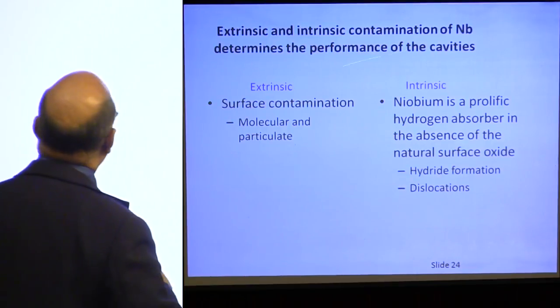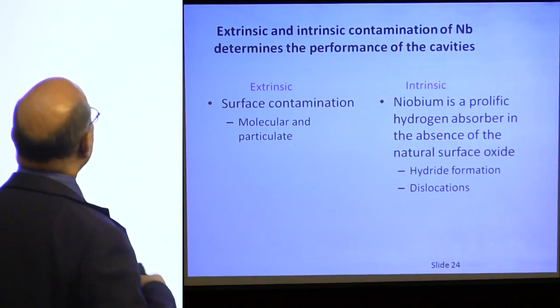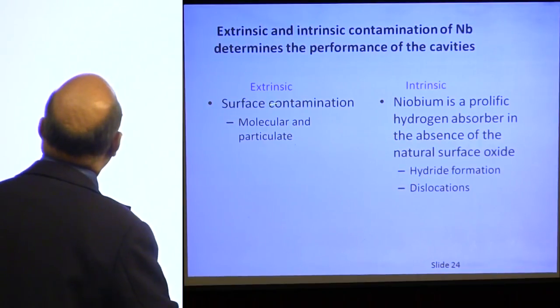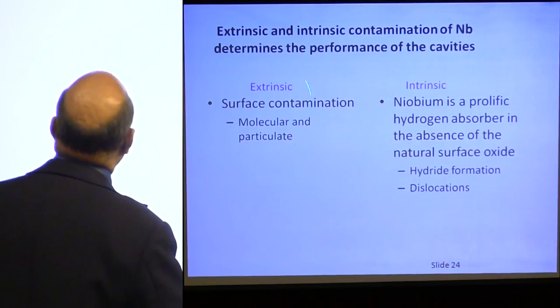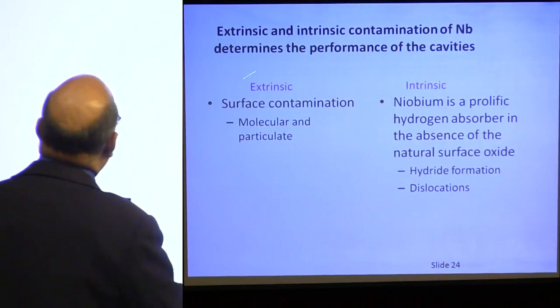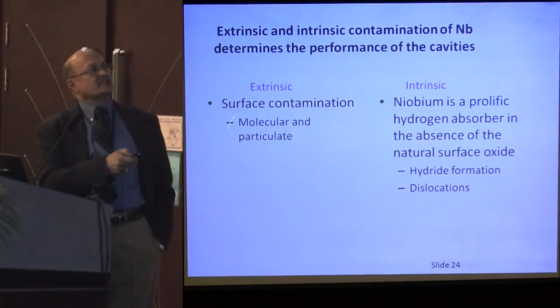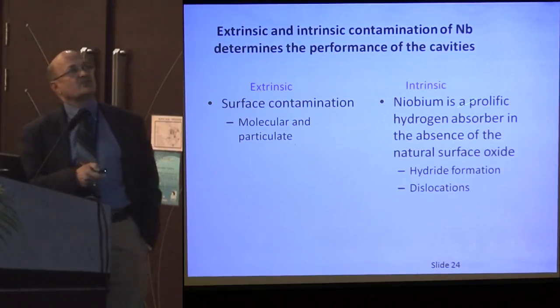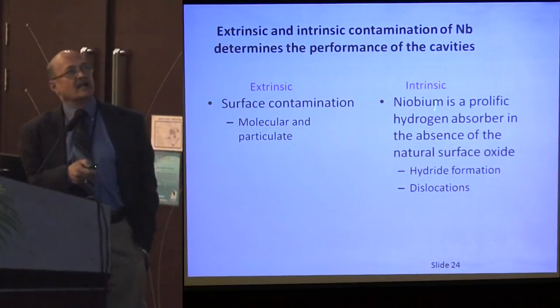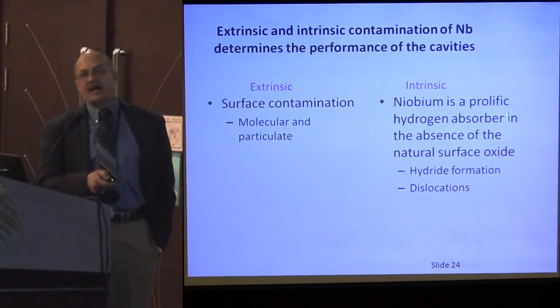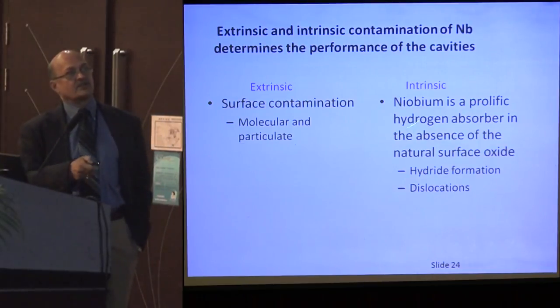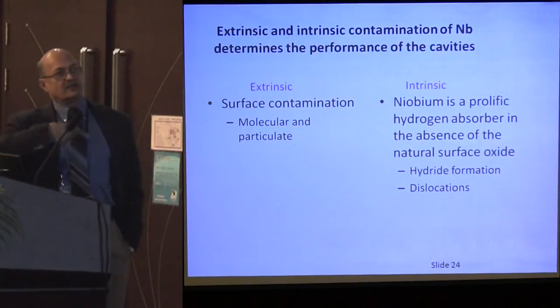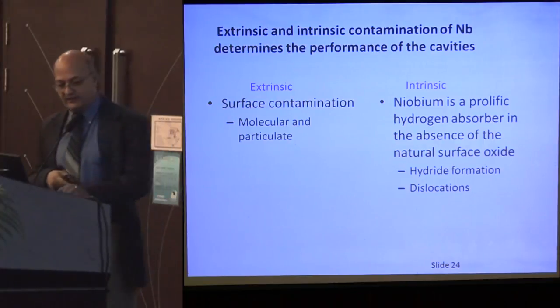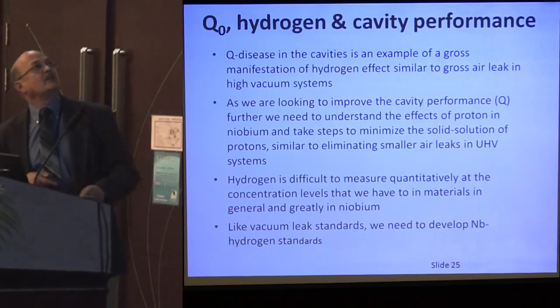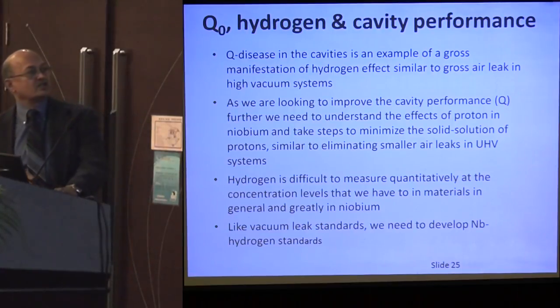Contamination on the surface of these cavities determines the performance of these cavities, and these can be divided into two groups, extrinsic and intrinsic. Extrinsic is mainly surface contamination, and we now understand the reasons for all of this, and we are able to successfully eliminate it. We still have some issues with intrinsic ones to get to very high quality factors, and the most important one is the absorption of hydrogen during the processing steps of these niobium cavities. Also, the dislocations that develop due to the forming of these cavities affect the surface resistance. As I said, the hydrogen plays a major role in this.